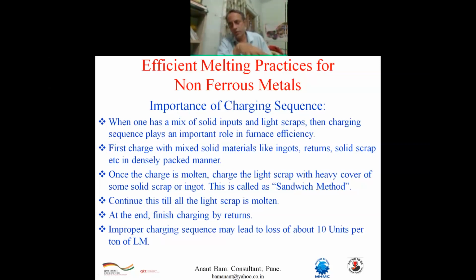Continue this process of sandwich method till all your light scrap ends. At the end, top up or balance your weight target by adding the known returns or ingot. Improper charging sequence may lead to a loss of about 10 units per ton of liquid metal. I have seen in many foundries that whenever they charge turning boring, they often put heaps and heaps of turning boring even on the top of the furnace crown. That should never happen. Why?